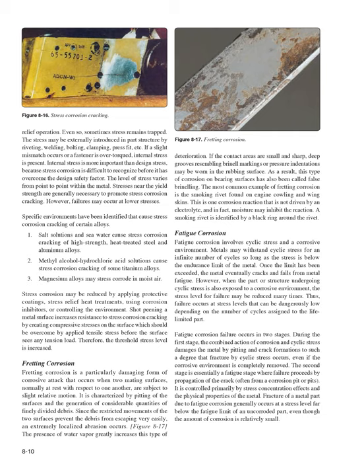Fretting corrosion. Fretting corrosion is a particularly damaging form of corrosive attack that occurs when two mating surfaces, normally at rest with respect to one another, are subject to slight relative motion. It is characterized by pitting of the surfaces and then the generation of considerable quantities of finely divided debris. Since the restricted movements of the two surfaces prevent the debris from escaping very easily, an extremely localized abrasion occurs. Figure 8-17, the presence of water vapor greatly increases this type of deterioration. If the contact areas are small and sharp, deep grooves resembling Brinell markings or pressure indentations may be worn in the rubbing surface. As a result, this type of corrosion on bearing surfaces has also been called false brinelling.